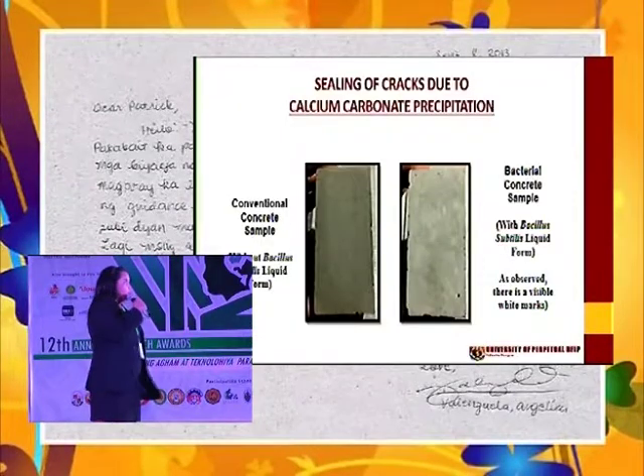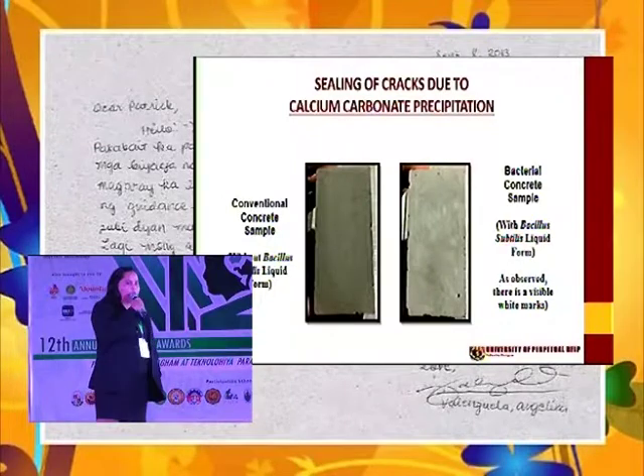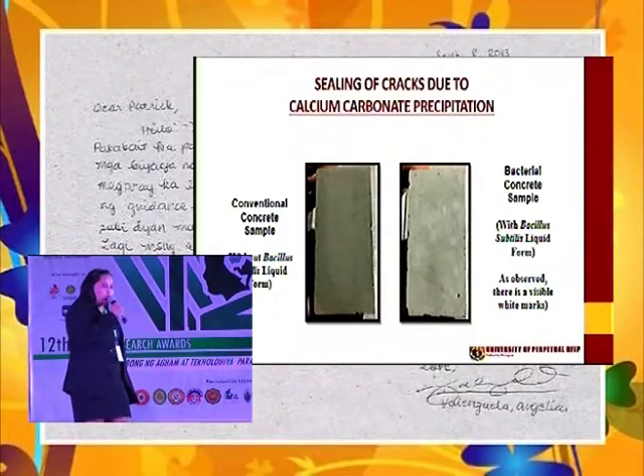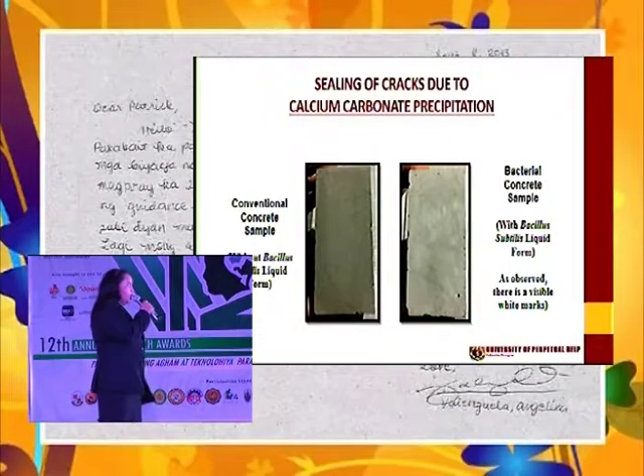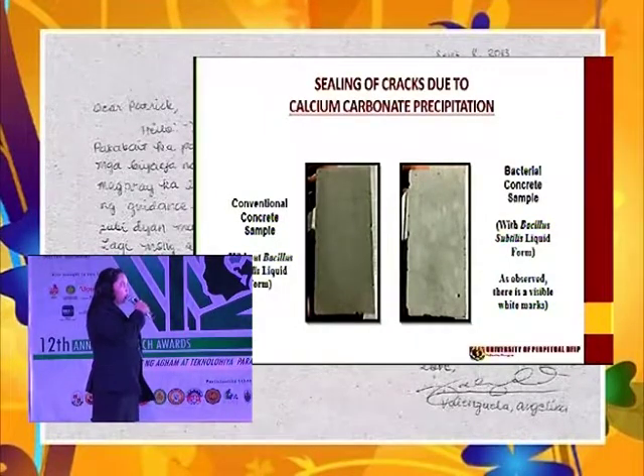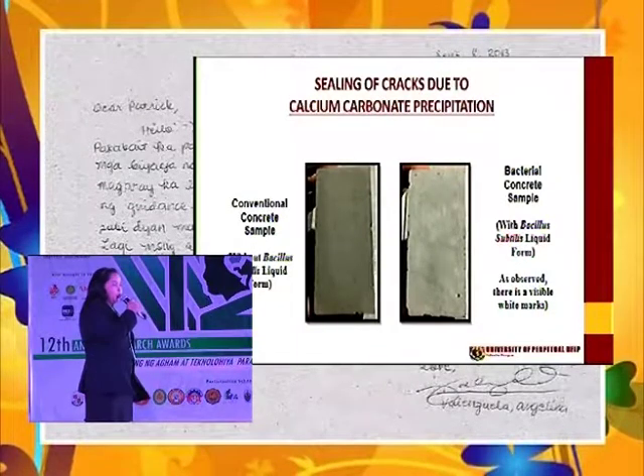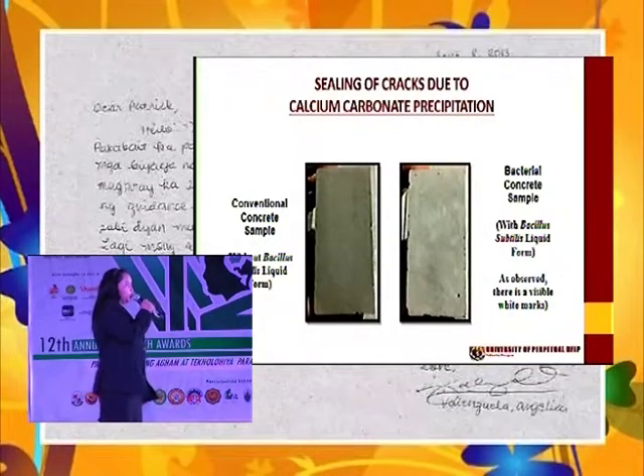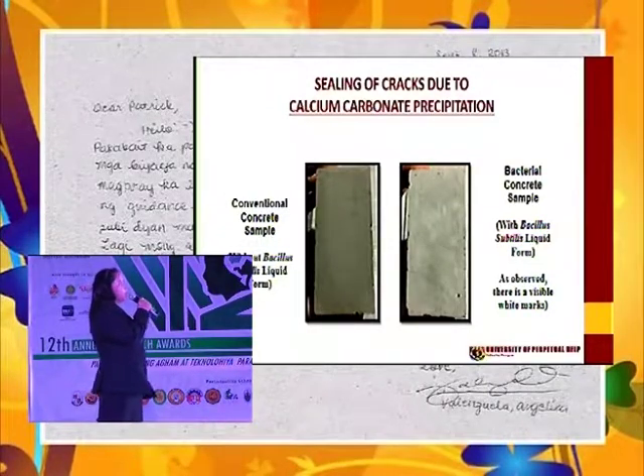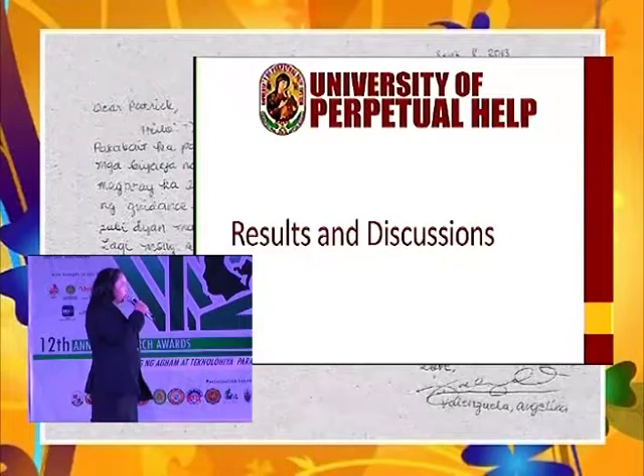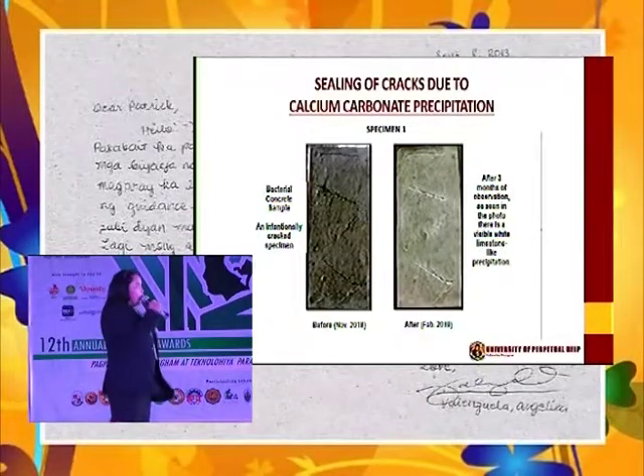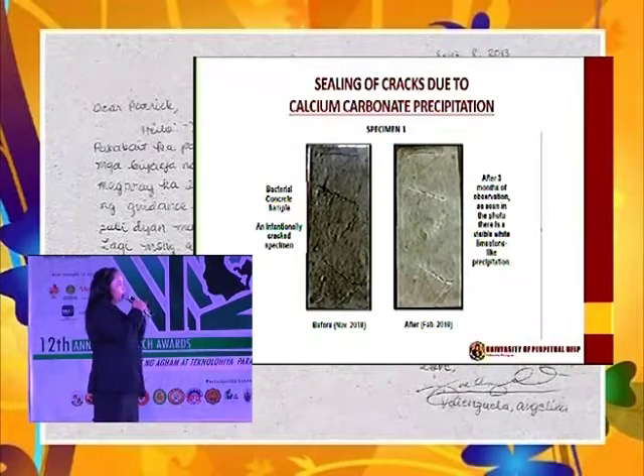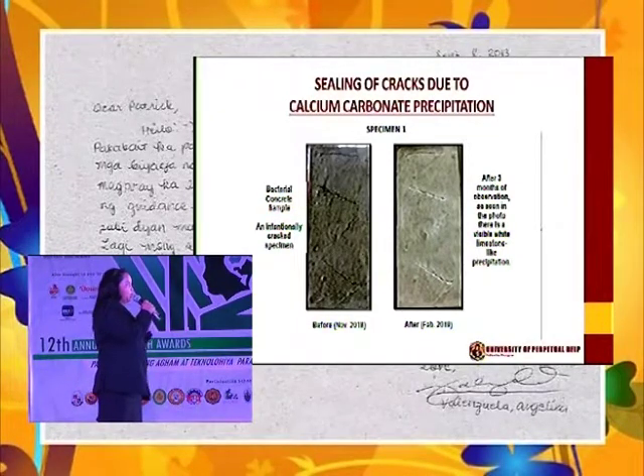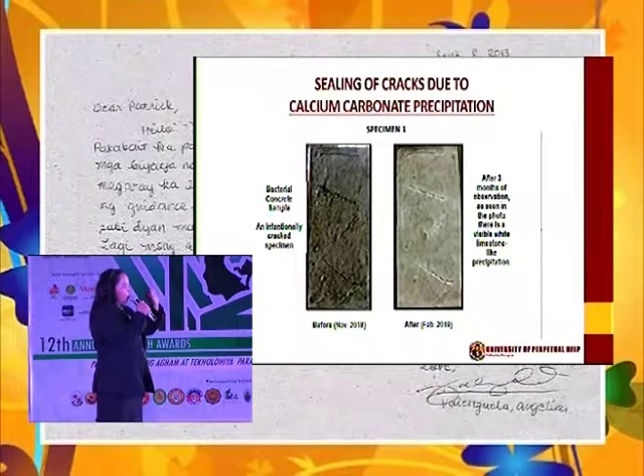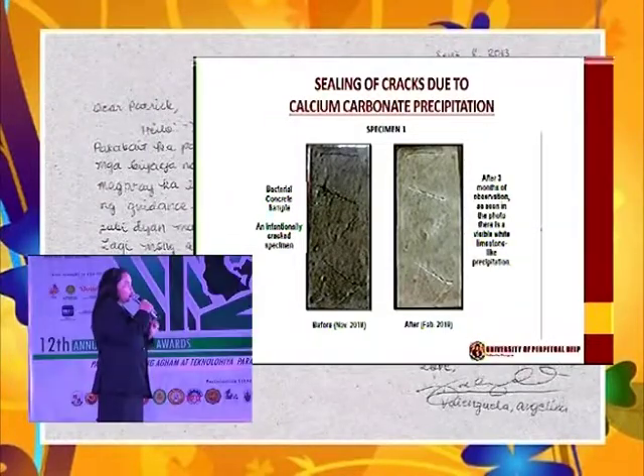Next slide, please. If you can see in the picture, we have two specimens: the conventional concrete without any bacteria, and on the other one, our bacterial concrete with the Bacillus subtilis. As you can observe, there is already calcite precipitation because of the white marks or white spots that are appearing. Next slide, please. For the results in our discussion, from November 2018 up to February 2019, there is a difference in sealing cracks, and you can see that calcite precipitation has already happened.